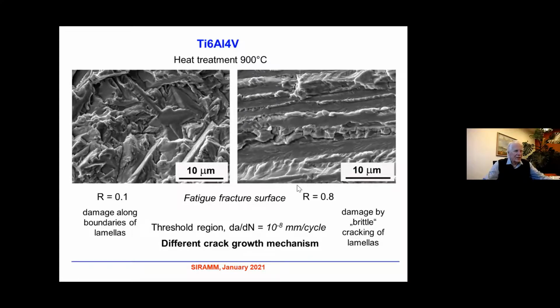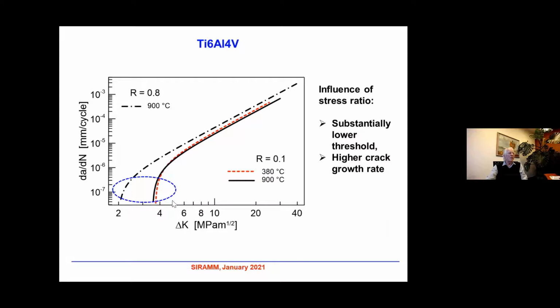On the other hand, for R equals 0.8, you can see that there is damage by brittle cracking of lamellas. So the crack is propagating perhaps slowly and then jumps, propagating slowly and jumping. And it is related to the microstructure. So we have observed a different crack growth mechanism in the case of the threshold region.